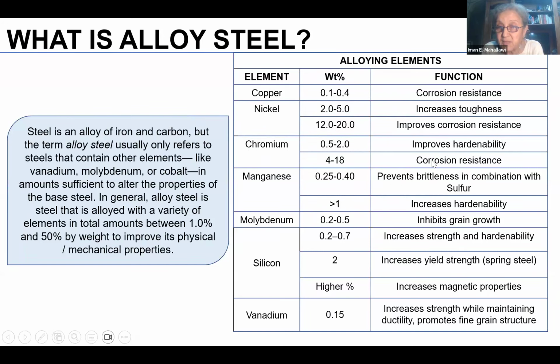And apart from forming the hard carbide, they also contribute towards the hardenability of the steels. We have also manganese, we have silicon, which do exist in conventional steels at certain smaller amounts, but we can also make use of them as alloying elements. So the background of the alloying elements and their addition to steel is always related to a certain range. We have to understand this very well, because within this range, these alloys are of benefit. But if we exceed the range, we may have some problems or some drawbacks resulting from the increase of their percentage.